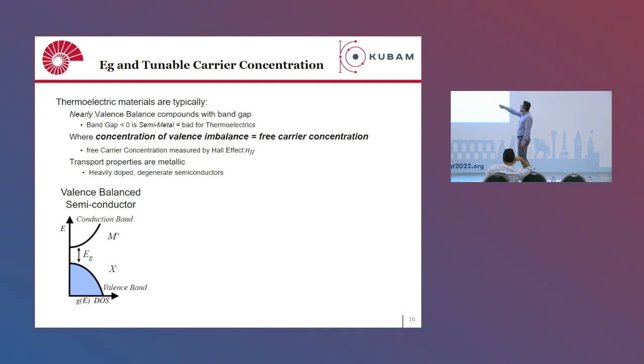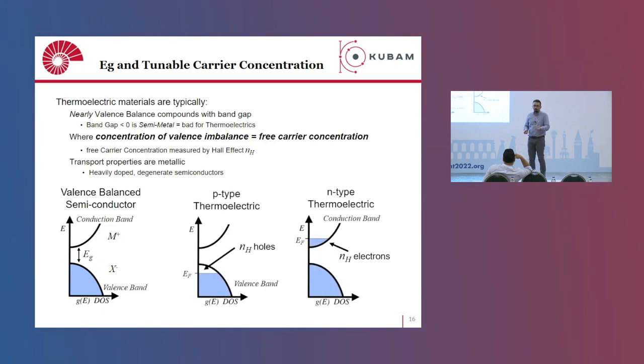So the first thing that we have to establish for good electronic transport is the band gap. Now materials should have a band gap, because if you don't have a band gap, then you have both types of carriers. So this band gap should be small enough so that you can dope this material either p-type, as you can see here, the Fermi level in the valence band, or n-type, the Fermi level in the conduction band. But it should also be large enough, as I said, so that you don't have two separate n and p-type carriers, like electrons and holes at the same time, which kills the Seebeck coefficient basically.